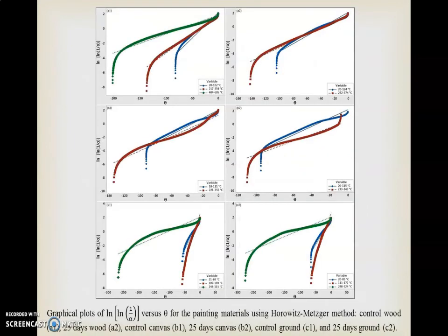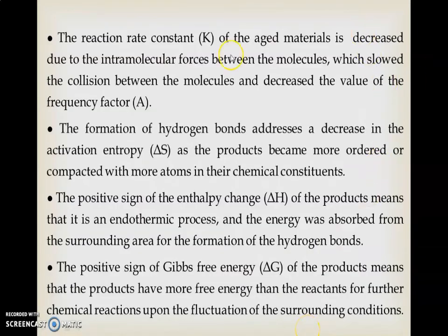We recorded the first order kinetics calculations and then the thermodynamic calculations by using the Horowitz-Metzger method. There was a decrease of the reaction rate constant as there are intermolecular forces between the molecules, which slowed the collision between the molecules and decreased the value of the frequency factors. Decrease of entropy as the products become more ordered. Positive sign of enthalpy means that it is an endothermic process and the energy is absorbed from the surrounding area. Positive sign of Gibbs free energy means the products have more energy than the reactants for further chemical reactions upon the fluctuation of the surrounding conditions.